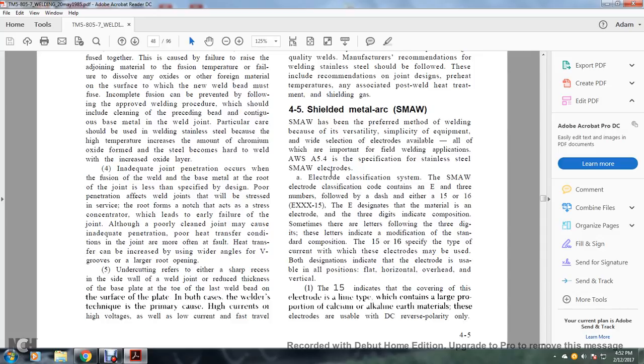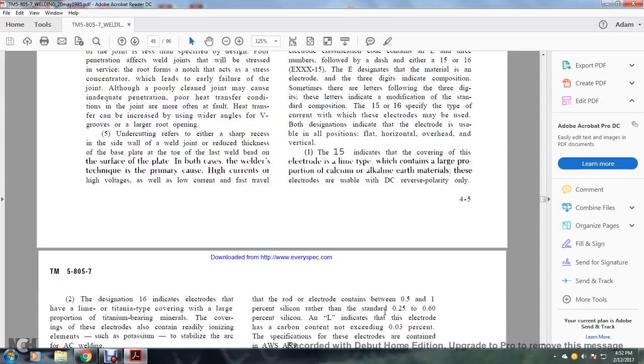Electrode classification system. The shielded metal arc welding electrode classification contains an E, followed by three digits, then a dash, and either 15 or 16. The E designates that the product is an electrode. The three digits indicate the composition. Sometimes letters follow the three digits, and these letters indicate a modification of the standard composition. The 15 and 16 specify the type of current the electrode may be used with. Both designations indicate the electrode is usable in all positions: flat, horizontal, overhead, and vertical. The 15 indicates the electrode covering is lime type, which contains a large proportion of calcium and alkaline earth metals, so these electrodes are usually used with DC reverse polarity only.